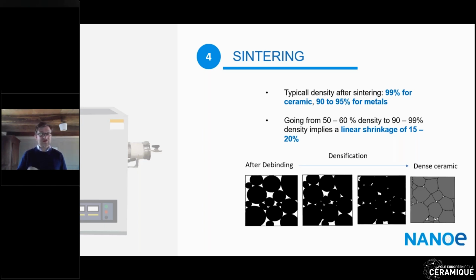applications. Obviously, going from a porous material to a dense material means there is some shrinkage. The porosity needs to go somewhere. And it goes outside of the part, and the part will densify and shrink. Linear shrinkage is usually between 15 and 20%, which is very significant and which is something that needs to be anticipated in the file preparation, and it will also have an impact on the precision and everything.